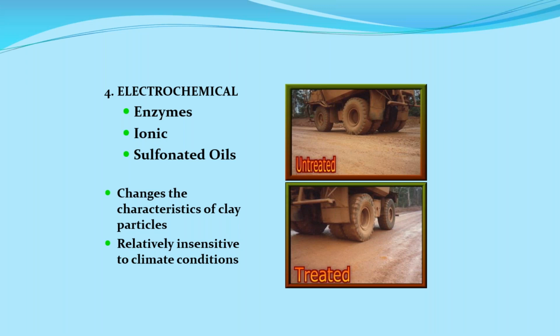And so he found that he could take a shell type of stone, which is a soft stone, combine it with a lava rock, which is a hard stone, and then as those two stones worked together and moved, the lava rock would break the shell down so that it would continue to create a binder to hold that road together. And then they treated that whole roadway with an enzyme that was specifically designed for that roadway. And like I said, he got 30 years out of it. That was pretty amazing.